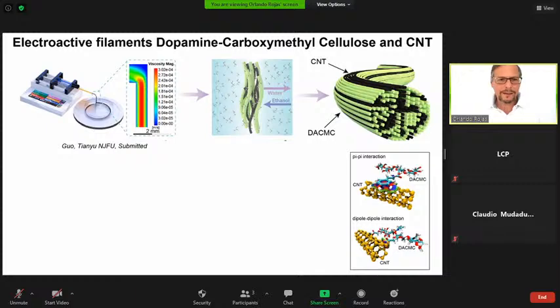One development that we have been doing in collaboration with Nanjing Forestry University is a different approach, also for wet spinning, as shown on the top, but using a cellulose derivative, carboxymethyl cellulose. And we have been playing with the idea of mixing nanocellulose with carbon nanotubes. This also has been tested by many research groups around the world.